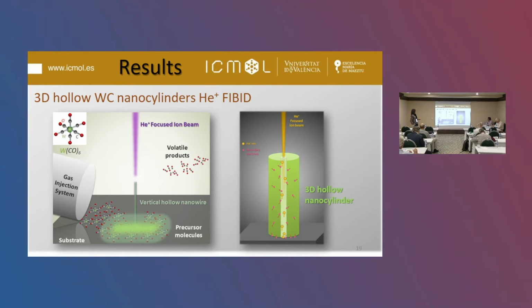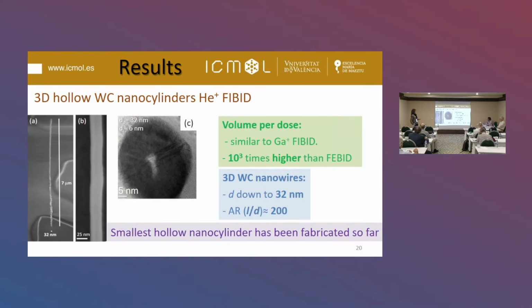The first effect is the growth of this nanocylinder. At the same time, the helium beam is producing a hole, a cavity at the center of the nanowire, due to the helium beam milling. So just using that very simple way, you can create such hollow nanocylinders of 32 nanometers in outer diameter and around 6 nanometers in inner diameter, and the aspect ratio was around 200. So it's something that we cannot create by using a completely different nanolithography technique. So it's a really huge advantage.